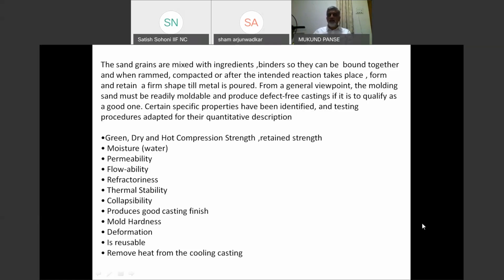Collapsibility means low retained strength so that decoring is easy and casting contraction is not hindered. It should produce a good surface finish. It should have good mold hardness. It should not deform. These are requirements of a mold so that sand erosion is avoided and the shape of the casting is maintained. Sand is reusable, so it is reclaimable and can be used again and again. And heat transmission from the casting should be good. These are the properties we seek from the sand mixture we are using.